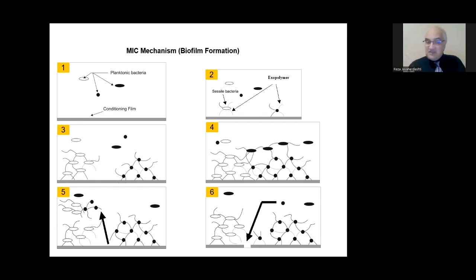And when that happens, as you can see in picture 5, you will have areas where you have biofilms and areas where you don't have biofilms, which are the best places for developing electrochemical cells, such as differential aeration cells, where low partial pressure of oxygen creates the anode and high partial pressure of oxygen creates the cathode. Picture number 6. And where the anode is developed, you will get pitting potential.